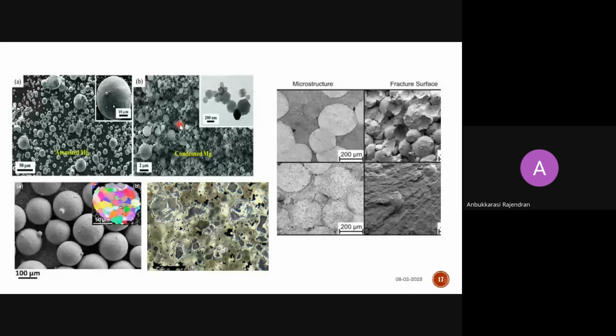Even after doing the process, you can see the agglomeration. Even for the powder metallurgy component, you can do regular sample preparation, then etching to reveal the internal microstructure. Again, this is the as-sintered condition of the powder metallurgy component, but partially it is not properly sintered. On the fractured surface, you could see the fracture of the particles itself. This is the fracture surface of the powder metallurgy component. If it is sintered well, you can see the proper merging, or a good bonding between the particles, the metals in the form of powder. Those samples' fracture behavior is different because of the proper complete metallurgical bonding between the particles.